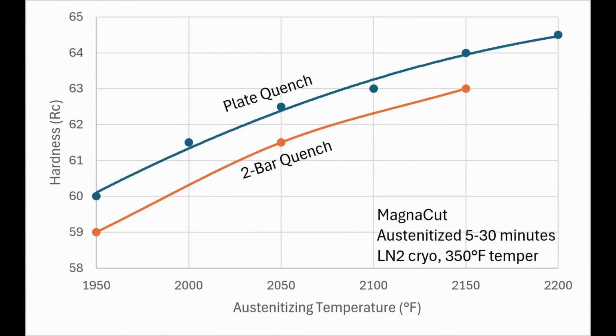Different steels can be more or less sensitive to these differences. MagnaCut has 2% moly in it, which increases its hardenability, so it is less sensitive to quench rate. However, a steel like AEBL has 0 molybdenum, and thus it can benefit more from a fast quench in terms of hardness. Of course, an oil hardening steel would be very soft even with a high pressure quench in a vacuum furnace. For air hardening steels, I have heard reports of up to 2 Rockwell C difference between a plate quench and a 2-bar gas quench in a vacuum furnace.